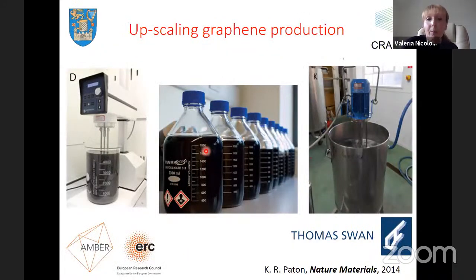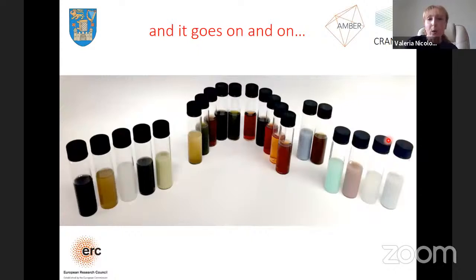So in 2014, we partnered with a company based in the UK, Thomas Swan, who wanted to take the science that we have produced in the lab, these 10 milliliter vials that we could produce, and upscale it for commercialization. So we developed methods which went away from sonochemistry. We went away from sonic baths, which are really not very easy to upscale. And the method worked extremely well with shear mixing. And this is, in fact, the method that the company is using to commercialize graphene now. And this is a small intermediate upscaled version where they are capable of producing 3,000 liters in about half an hour nowadays.